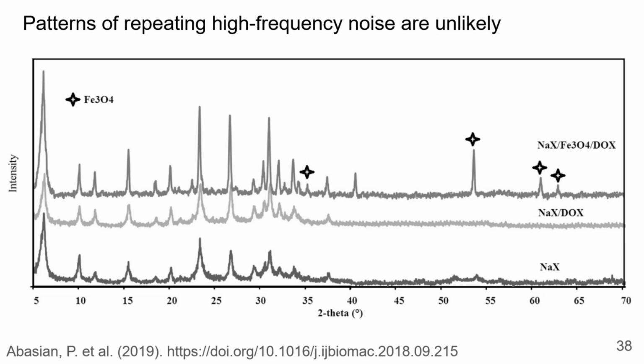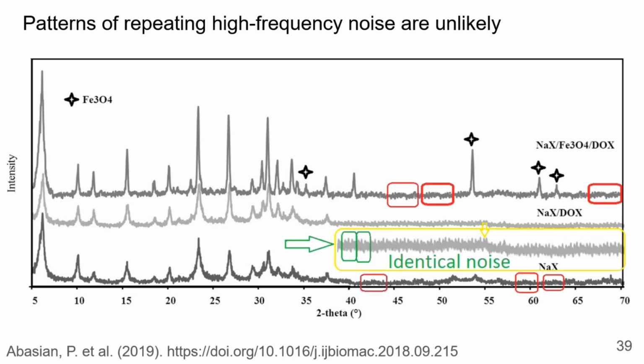But if you take a closer look at this pattern, you can see, as denoted by these red boxes here, there are regions of this pattern where the noise repeats. And there are probably 100 different data points in this small fraction of the pattern here. So it is incredibly unlikely that you would see this pattern repeating.